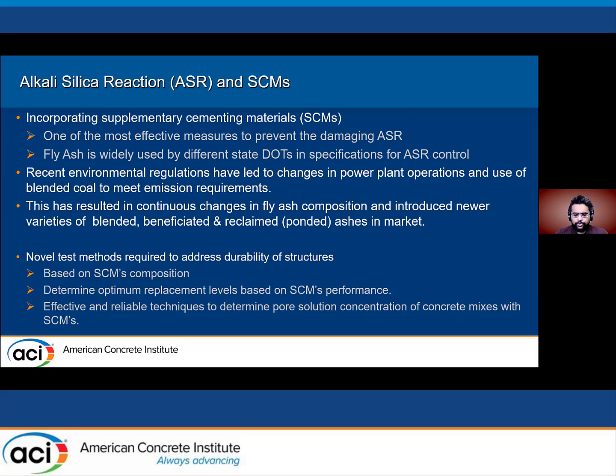So this points to a very important fundamental aspect: any new test method, to be applicable, first has to address the performance, which has to be a function of the composition of the SCM. As the nature of the SCM and the fly ash composition change, the performance would be changing as well. So these test methods need to address the performance based on the composition. And on that scale, the pore solution is the first aspect that we would be looking at.